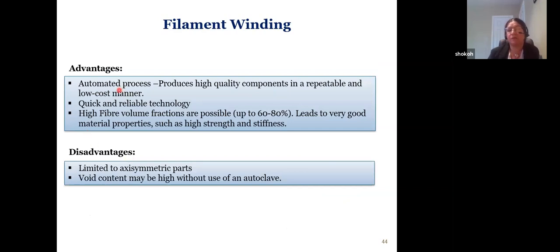The advantage is it's an automated process. It gives you high quality and repeatability. And the cost, when you look at autoclave, is much cheaper, a low-cost manner. Quick and reliable technology, it gives you a very high volume fraction of fiber inside. You can put as much as 80%. And that brings us very good material properties, and I can get high strength and high stiffness.